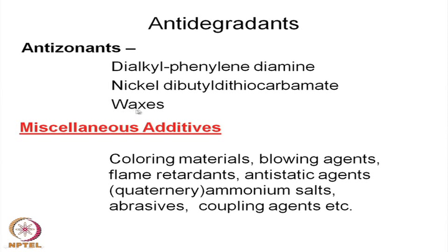That wax is saturated, so that saturated thin coating prevents ozone entry to the vulcanized rubber surface. So, that prevents degradation by the action of ozone.